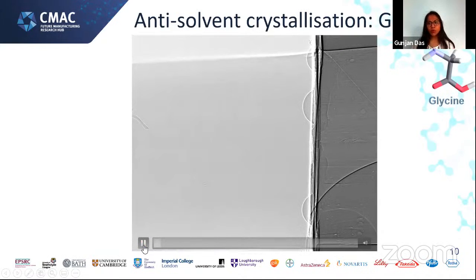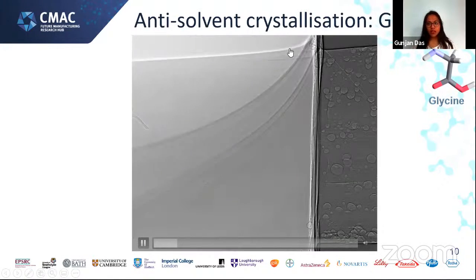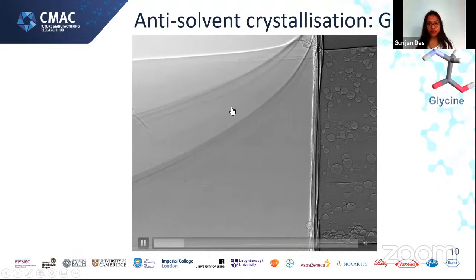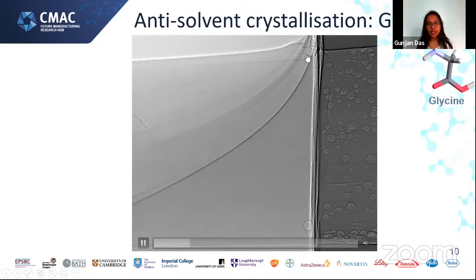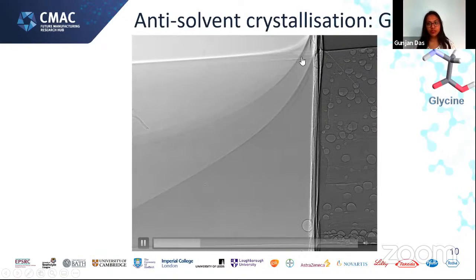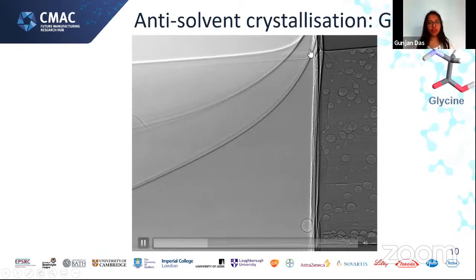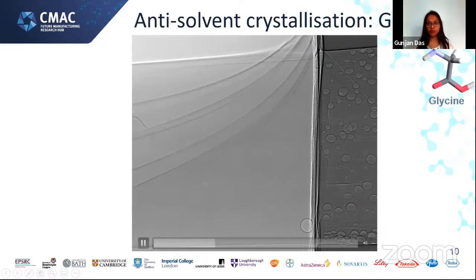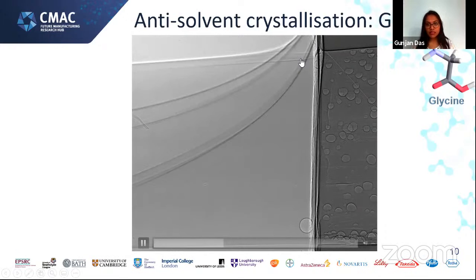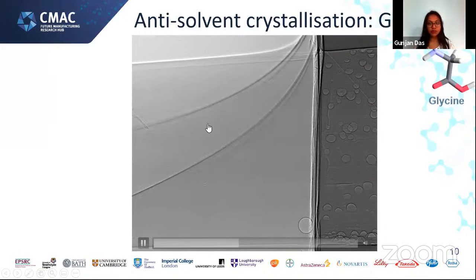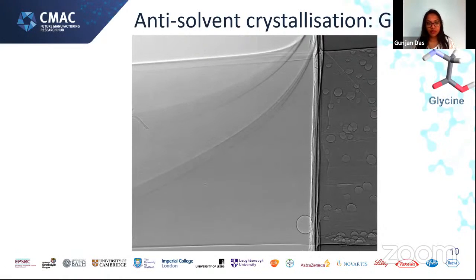And what we can see is the inner tubing flow and these boundaries as well. You can see here the heterogeneous nucleation of a crystal, which just got flushed away due to the high flow rates we have. As you can see, these boundaries actually are always there, and you can see them moving back and forth, of course, simply because the imaging was done very fast.